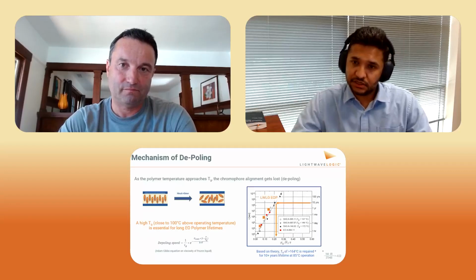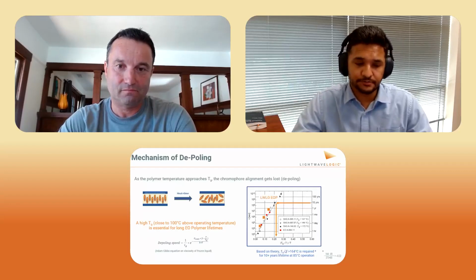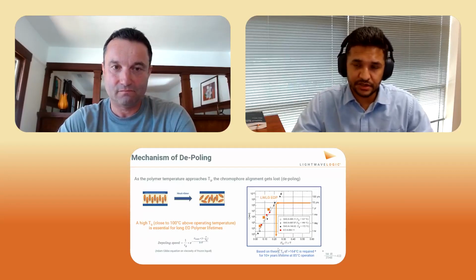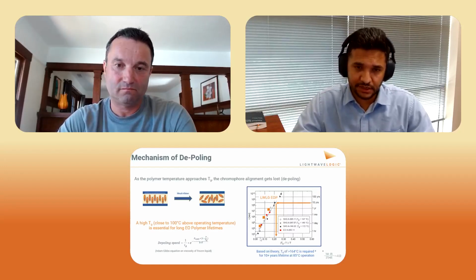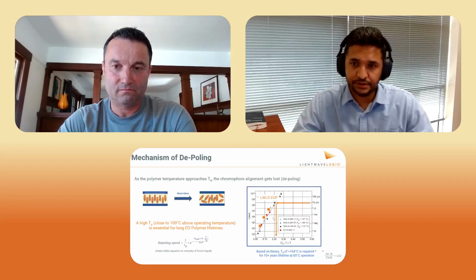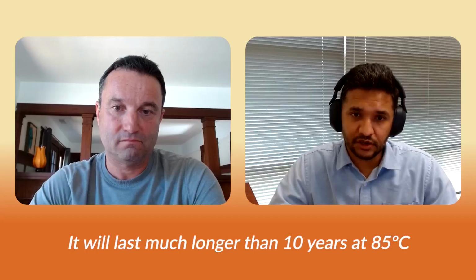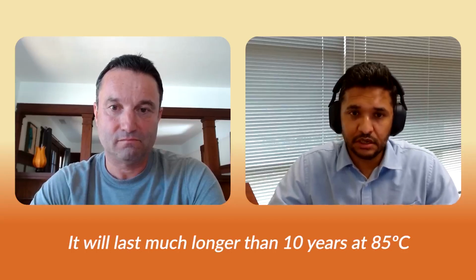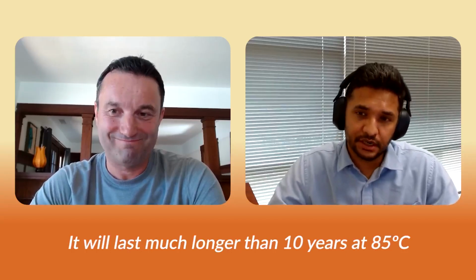And then what we did is we performed reliability thermal stress tests on our chromophores. And what we found is our chromophores actually match or even better the slope that was reported, so that we are very confident that it will last much longer than 10 years at 85C.